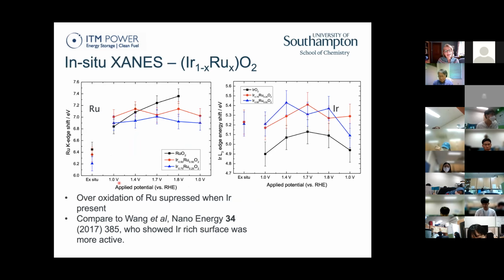What we can see is as we change the potential, if you just start off with a ruthenium sample, the edge is shifting. So the oxidation state of the ruthenium is really changing, right? But when we add the iridium, we suppressed that oxidation state change of the ruthenium. So we're stabilizing it somehow, stabilizing the ruthenium.